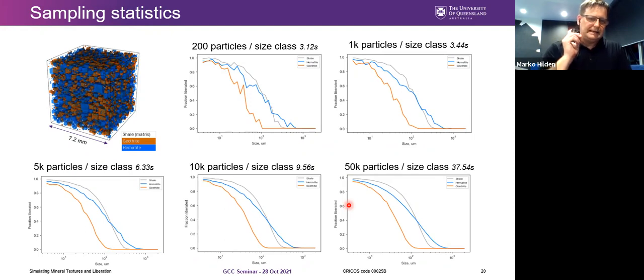So you are sampling the texture many times, and the more you sample, the smoother these distributions become. If you were to sample just 200 particles per size class, you'd get a really wavy distribution. As you sample more, you get a smoother distribution, but the simulation time also goes up. So I typically go for around 10,000 particles per size class for a relatively high grade texture. This is with 40,000 grains, by the way, in this texture.